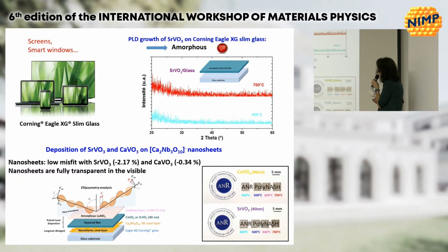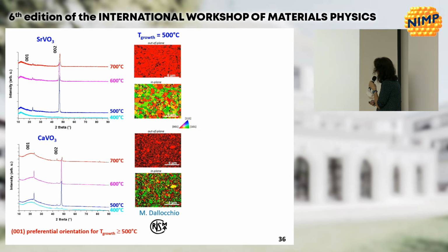Nanosheets present low misfits with both vanadates, and they are also fully transparent in the visible. So the stack is the following: you have a glass substrate, a nanosheet, then the films made by PLD, and then an amorphous capping layer to protect the vanadate films. As a result, as you can see, all the films grown at different temperatures are transparent, and more important, they are crystalline.